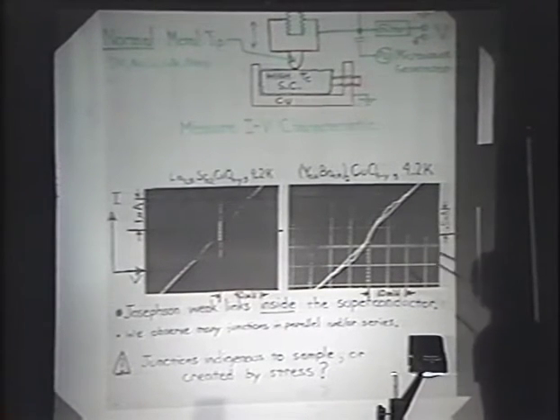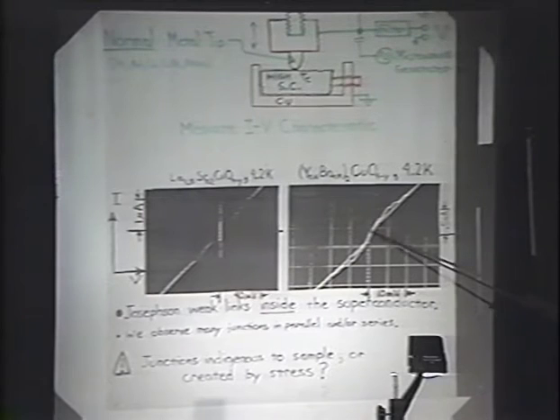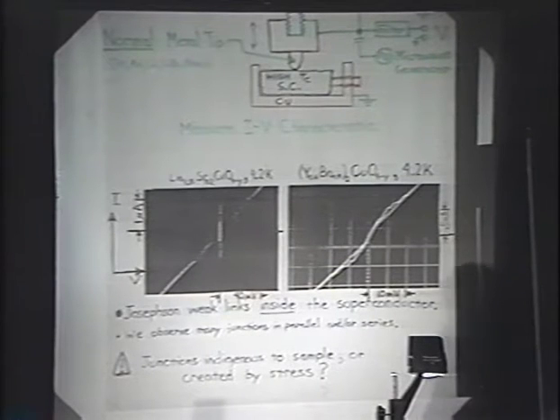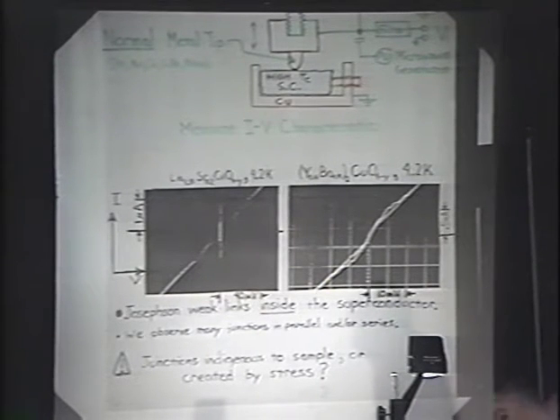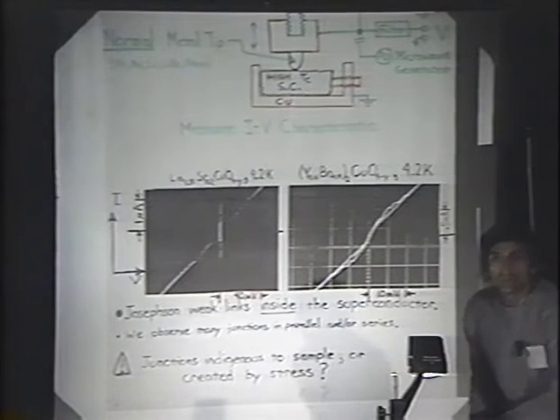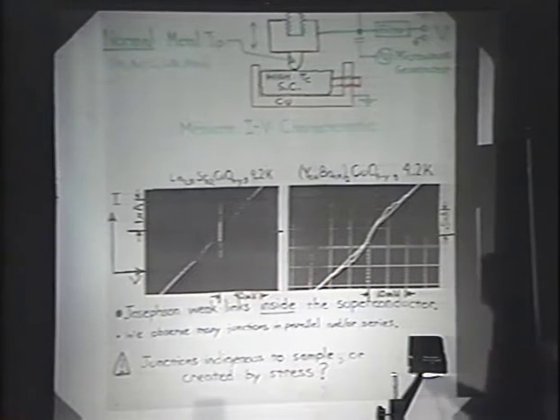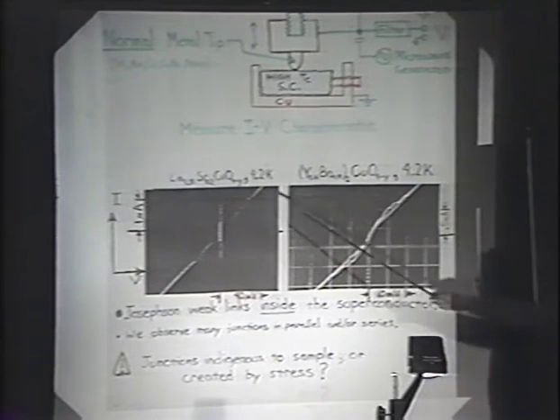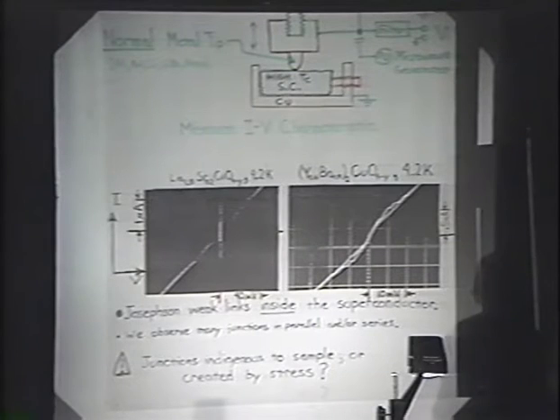In this case here, we have a weak link with some shunt resistors. Actually, we have several weak links, maybe in parallel and in series. Now, the only superconductor in this circuit is this high TC superconductor. The tip is normal metal. So these junctions have to be coming from inside the high TC superconductor, presumably near the tip, because that's where the current densities are the highest.